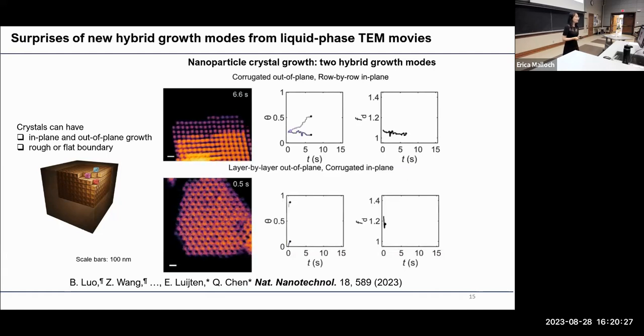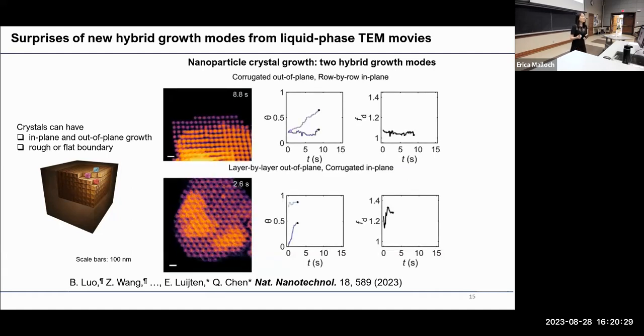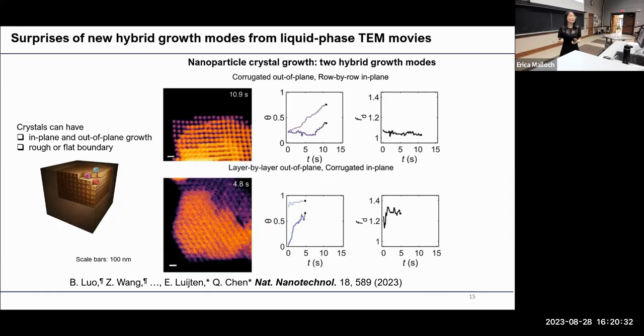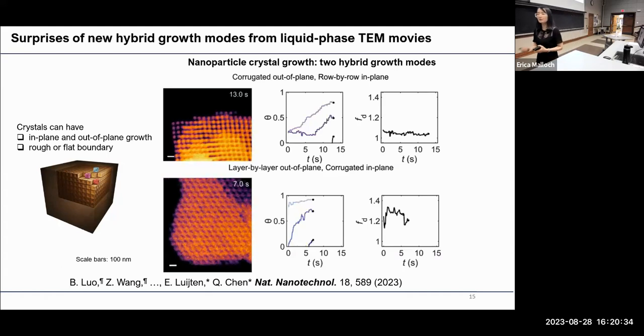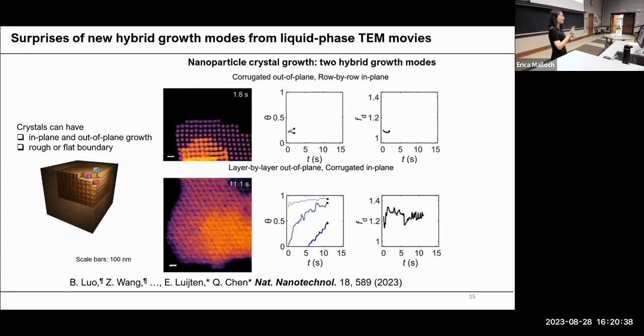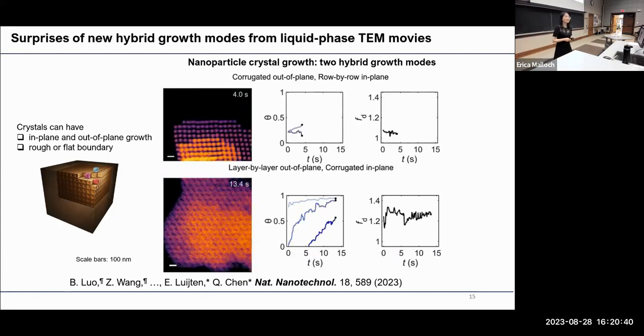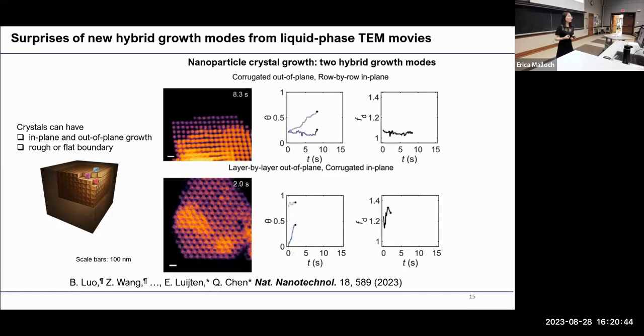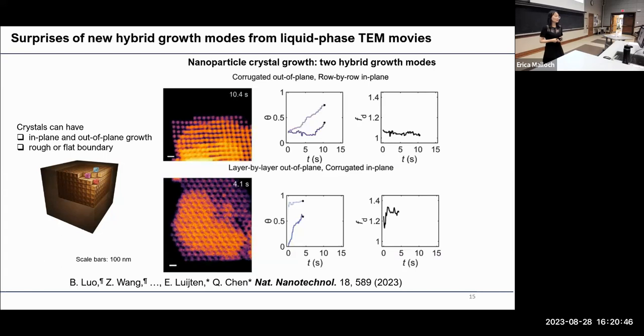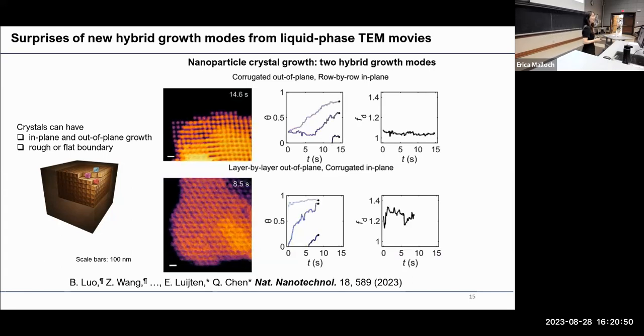And then in comparison for the movie below, the 2nd layer will only start to grow when the 1st layer stops growing. So that means out of plane is layer by layer growth. But if you look at each plane, the boundary is actually really rough. So in plane is corrugated growth. So this is also the first time we were able to capture those 2 hybrid growth modes in solution in real space and real time.